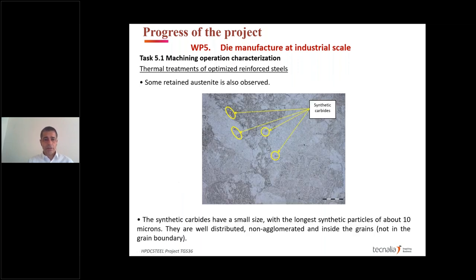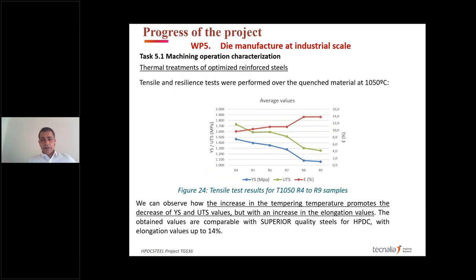We checked the distribution and agglomeration of the particles in this case, and also the elongation, yield strength, and ultimate tensile strength values. We can see here that if we increase the temperature, we promote a decrease in the yield strength and ultimate tensile strength values, but we increase the elongation. So we get good elongation values, up to 14%. After that, we have a point where the best working area was this area.